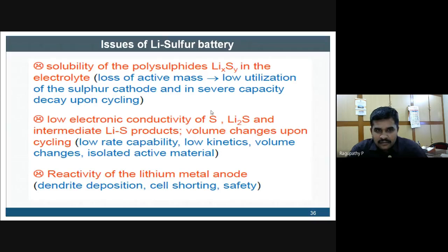In the case of lithium-sulfur, look at this. Though the energy density is much higher compared to a conventional battery, 3,500, look at the challenges in that: solubility of polysulfide, conductivity, and the reactivity of the metallic lithium. So what we thought in the very beginning, when they started this technology with lithium as an anode, the dendrite growth is common in the case of lithium-sulfur or lithium-air, because there we are not going to replace this metallic lithium.